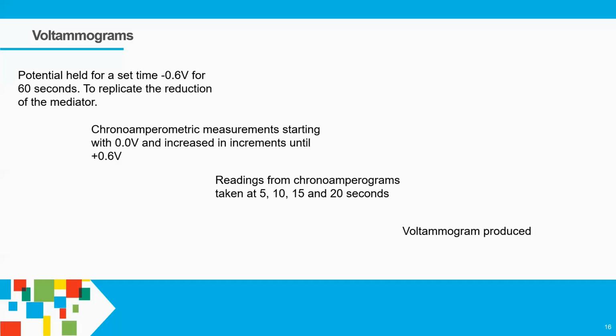We have a set concentration of mediator. And we're just basically going to reduce that mediator in the same way as if you had a really good system where the enzyme is fully reduced in the whole system. We then get chronoamperometric measurements, and we will start from 0.0 volts and then increment up to 0.6 volts. And we'll take the readings at 5, 10, 15, 20 seconds, and then we produce our voltammogram.